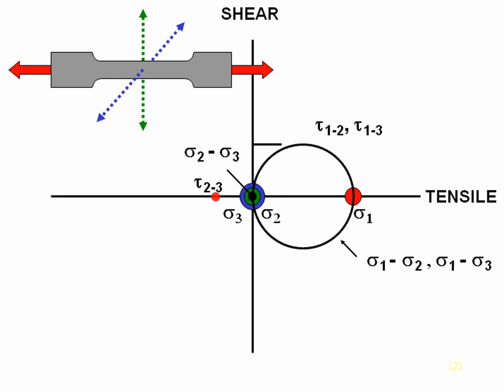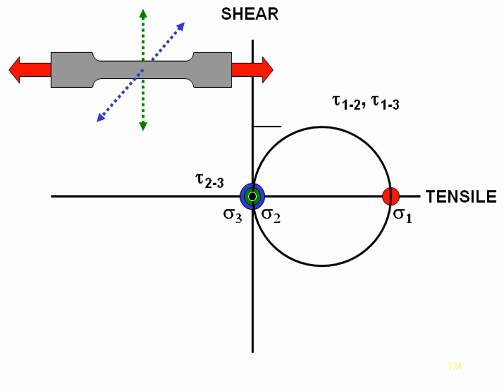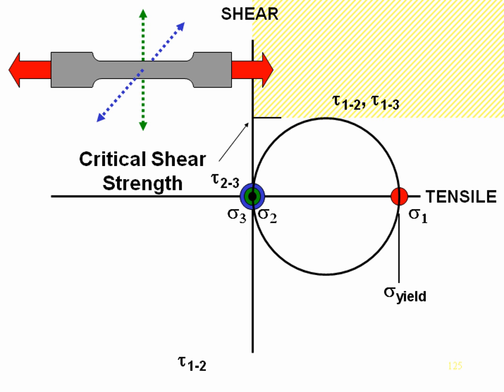Now, if I increase sigma 1, my circle gets bigger. And my shear stresses start to increase on shear plane 1, 2, and 1, 3. Of course, 2, 3 doesn't change. It stays at a value of 0. If I increase my stress even further, I finally get out to what I call the yield strength of the material. Even though we commonly use that term, I think it's an unfortunate use of terms. Associated with that yield strength stress are shear stresses that exceed the critical shear strength in the material. Now, it's because these shear stresses exceed this critical shear strength that I finally get some deformation.